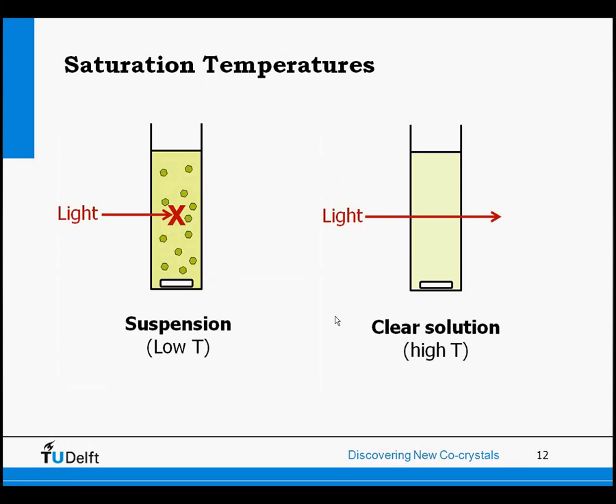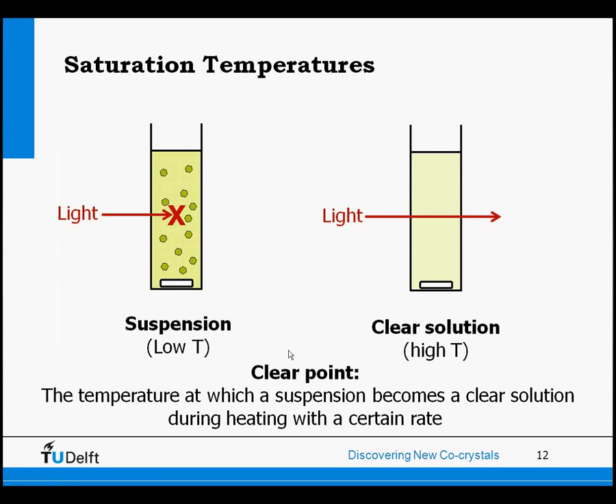So we measure saturation temperatures. You start with a suspension, and light is going through this suspension. It is actually blocked because the crystals are present. And at some point you will get a clear solution, and light is going through the sample, so that you can really measure that you have a clear solution. That clear solution will be at high temperature, and the suspension will exist at low temperature. We are interested in the point where these crystals disappear, so the clear point, the temperature at which a suspension becomes a clear solution during heating with a certain rate.